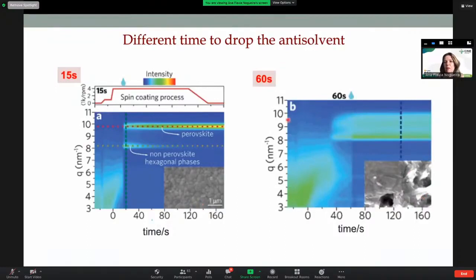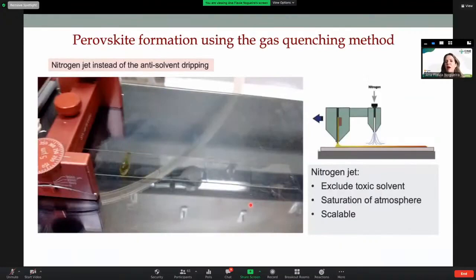The point here is that you have to drop the antisolvent while you still have the signal from the precursor solution. So there's a reason that this antisolvent method is the most used method to prepare perovskite. It's something that you can do in the lab, but not when you're really thinking about going to more scalable, large area.